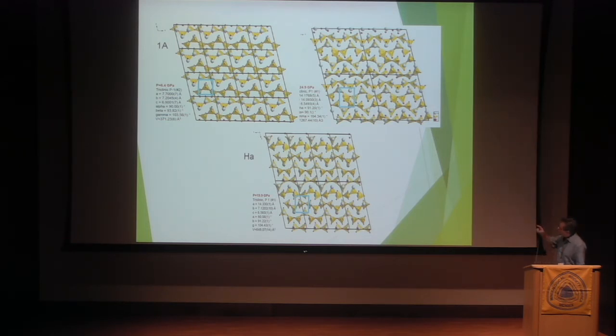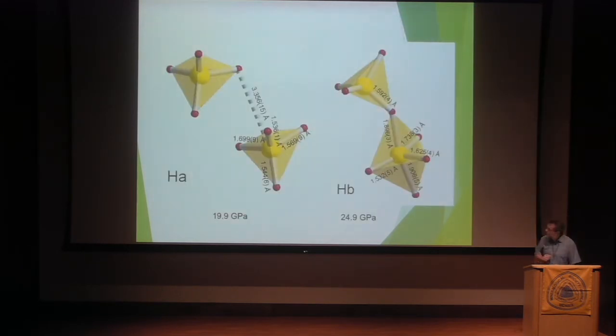But we found a sequence of 2 phase changes. One of them transforms 4-coordinated silicon, one of the silicons in this low symmetry structure, into a penta-coordinated silicon. This is how it looks in zoom. So we have a simple rotation of a tetrahedron, which brings one of the apices of this coordination polyhedron to a close vicinity of the neighboring silicon, forming a 5-coordinated state.